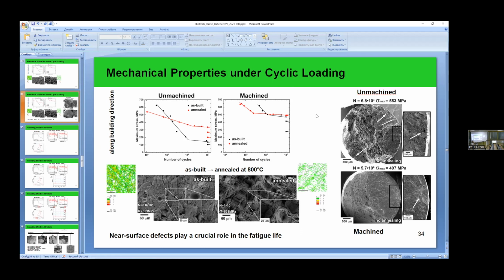In the case of the machined samples, we spend more time on crack formation. And in this case, since we deal with higher stresses and higher loads, the propagation of the crack is not so sensitive. Plus, it's possible that there are also contributors like the formation of these nitrides. They may also contribute to the fatigue life, but it's just our assumption.